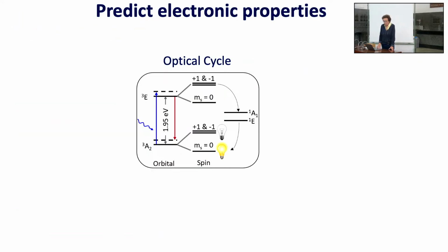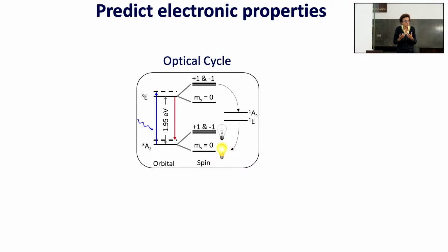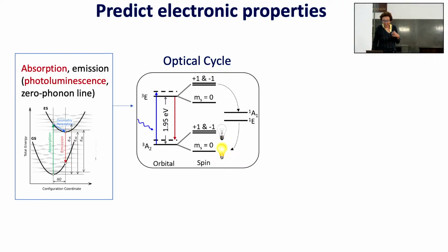So suppose that you have a diamond lattice, and in your diamond lattice, you create a very tiny point defect. For example, a nitrogen vacancy. You remove one carbon, you put one nitrogen, and you charge it negatively. And then you create electronic states in the gap. This is what those states are. And then with light, you create a cycle that you use to interrogate your defect and to prepare your coherent state. So you need to understand, again, light matter interaction, absorption, photoluminescence.